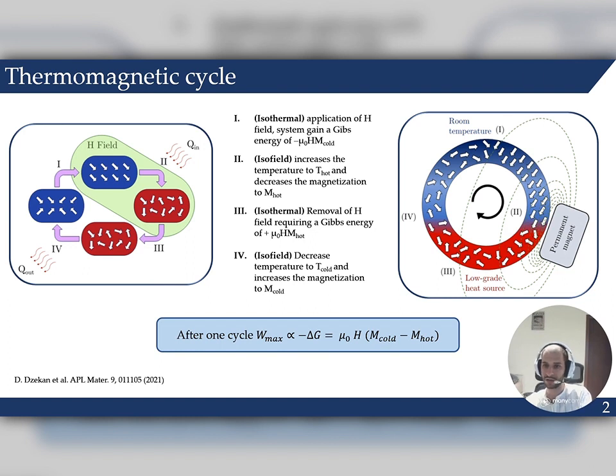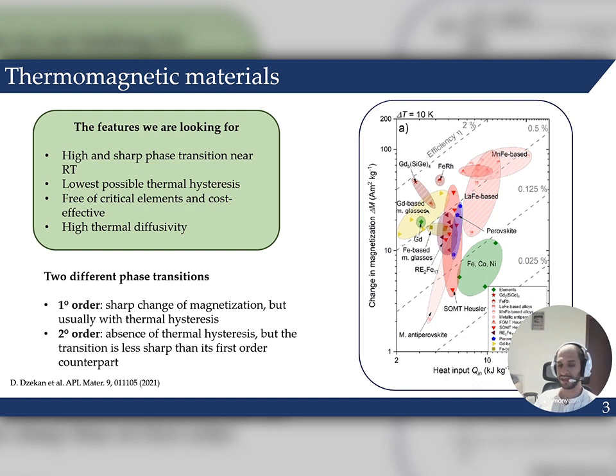On the right of the slide you can see the operating scheme of the thermomagnetic device that we developed to test different materials. But which kind of material are we looking for? Well, in general, thermomagnetic materials should present a magnetic transition near room temperature, and in the case of a first order transition, its thermal hysteresis should be as low as possible. Of course, they also should be possibly free of critical elements and cost effective. But finally, they should also have a high thermal diffusivity to exchange heat quickly and to increase the speed of the cycle. On the right of the slide you can see that the scientific community is evaluating a large number of families of material for this kind of application.